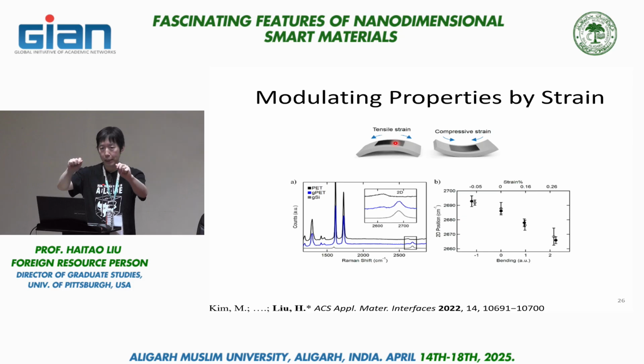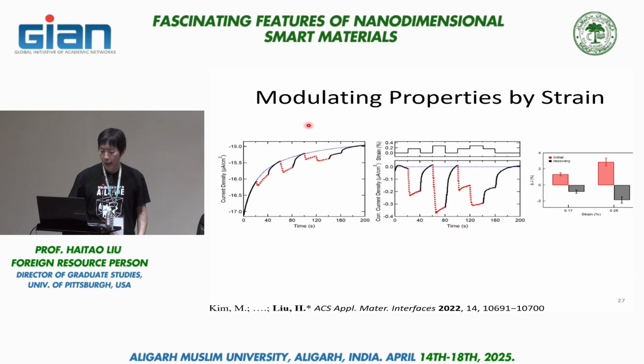Then what we did is we bent it in different directions, and then we used this graphene substrate as an electrode, and we did a hydrogen evolution reaction on this electrode. So this is the data. What we did essentially is we altered the strain as a function of time. So if you look at this one, the strain is 0, and then we apply positive strain and then come back to 0, and then after some time we apply even greater strain and then come back to 0. So we are essentially doing this bending, not bending, bending, not bending, a different amount of bending, and the amount of bending would create different kinds of strain.